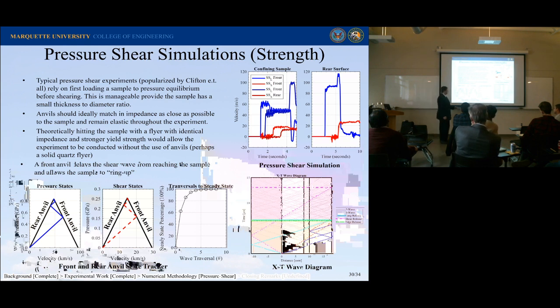And you can see right here I'm trying to do different timings to make sure that my longitudinal waves fully ring up my sample in 3 waves, 1, 2, 3, which is about 95, 96%, before this shear wave arrives right here. And then this is my timing window where I'm allowed to measure each of these different states. So between here and here I measure the pressure state of 1. Anyway, just a bunch of optimization there.